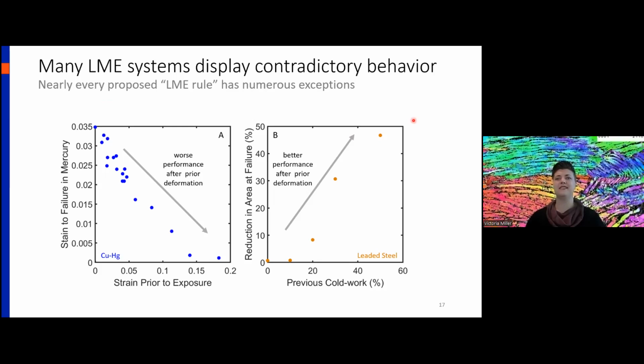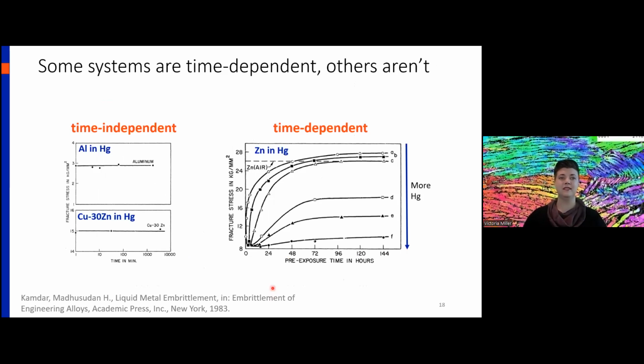And this is emblematic of sort of every liquid metal embrittlement rule that's been proposed. They all have numerous exceptions. It's very confusing, or it seems to be. Another example is some systems are time dependent and others are not time dependent. So this is aluminum and a copper zinc alloy in mercury. Here you can see that as time progresses, the fracture stress doesn't change at all.